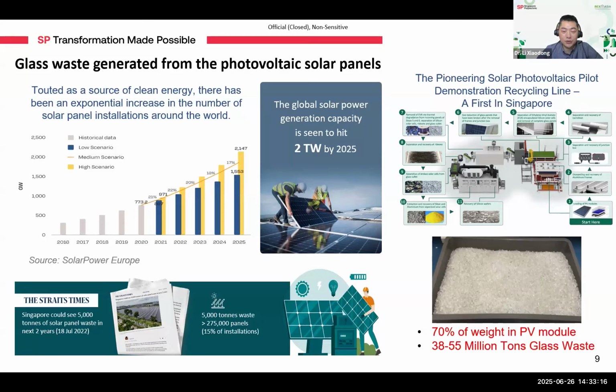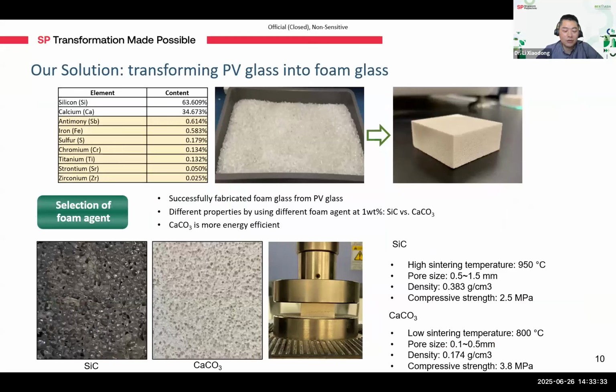But here's the issue. The glass makes up about 70% of a solar panel's weight, translating to about 38 to 55 million tons of recycled glass that need to be safely managed. Looking at the element content of the PV glass, which, like other glass, primarily consists of silicon and calcium, with additional metals such as chromium and titanium. So it is important to find a safe recycling solution for it.